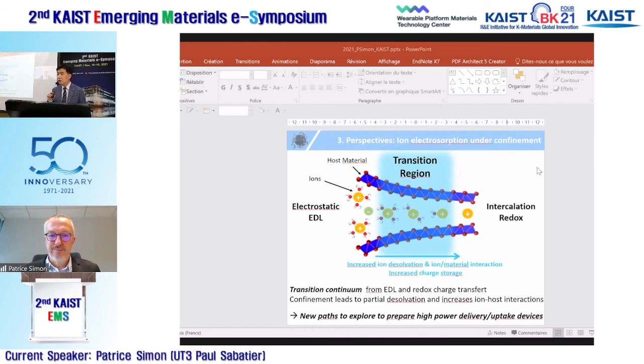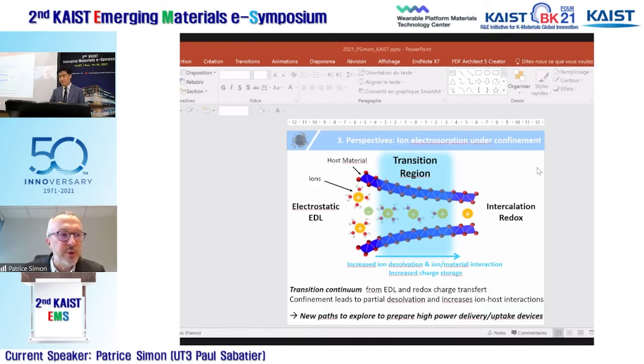Okay. The last question from the student. Thanks for the wonderful talk. I wonder if the partial desolvation can occur in a reversible manner during charging, discharging. Yeah, this is an excellent point because maybe I was not clear enough on that. But the partial desolvation that we observed in porous carbon was fully reversible. This is what we published with Yury 15 years ago. So obviously in MXene materials, in these 2D materials, this is the same. This is reversible during charge and discharge. So you have a desolvation, resolvation. This is what is really interesting. It's not a single irreversible process, not a single shot process. Okay. Thanks for giving me the opportunity to clarify.